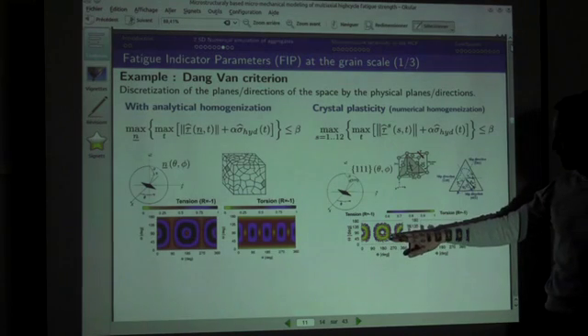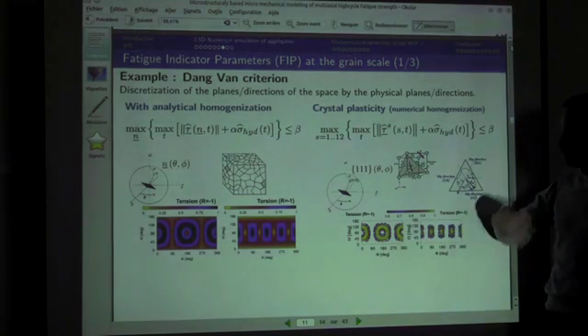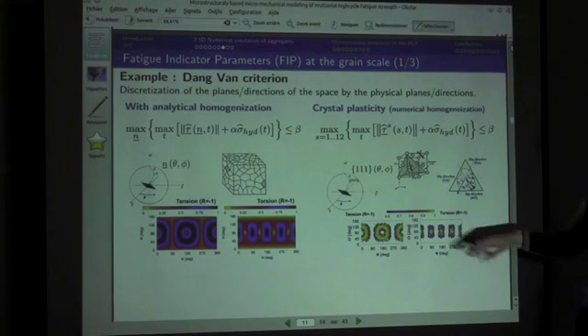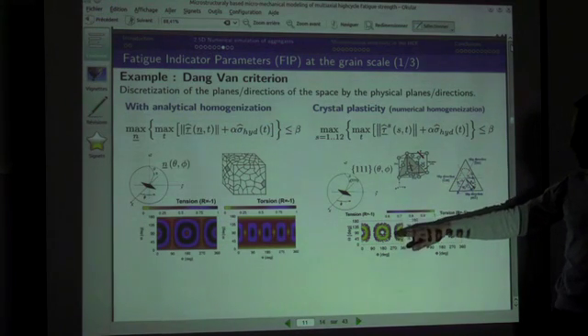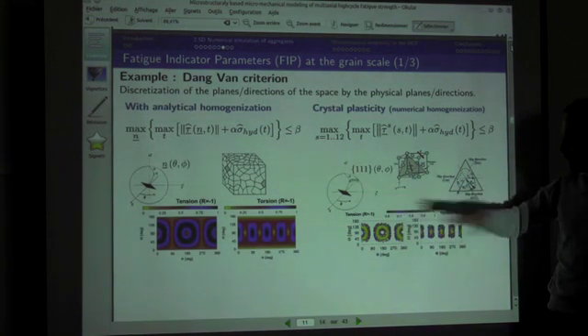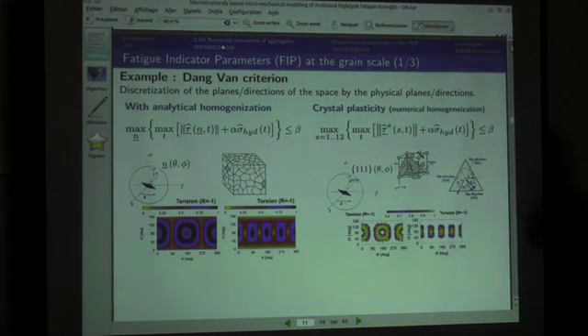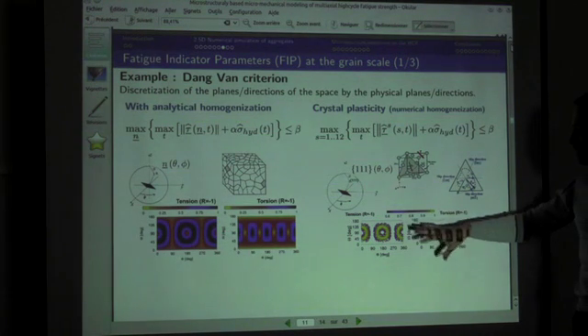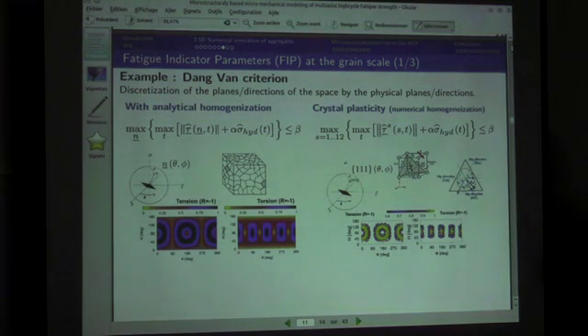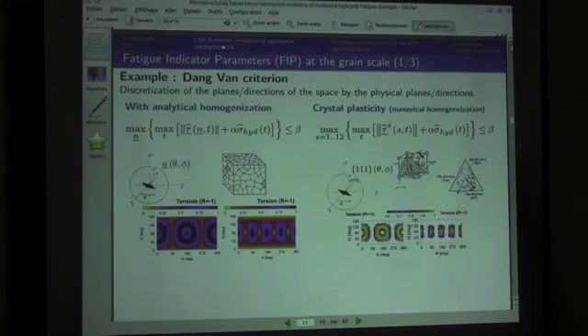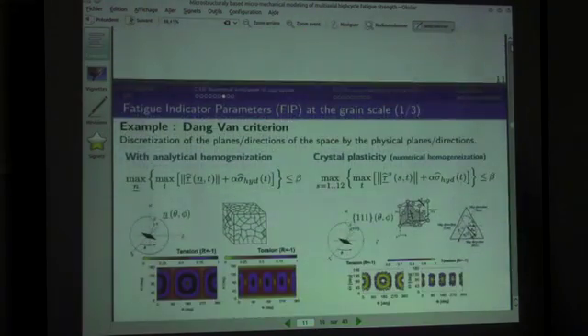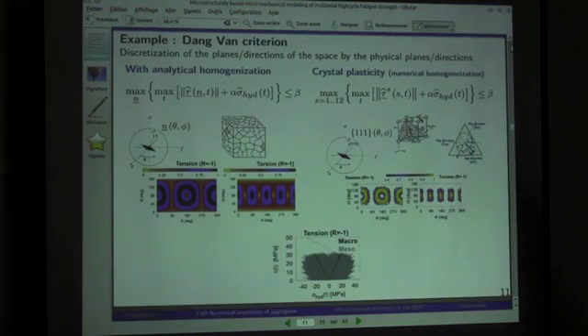And what you can see here is that you limit the analysis to some particular planes first, and then you input some noise. Here it's more or less continuous, and here you have a noisy picture of the fatigue parameter. And this noisy picture is related to the fact that you are using anisotropic elasticity. Then you go from isotropic elasticity to anisotropic elasticity, then you change the picture of the parameter as it is.